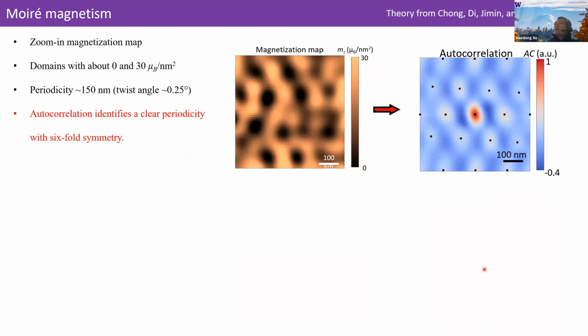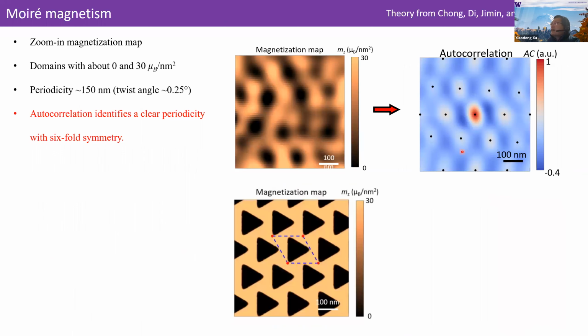So we perform similar data analysis using these autocorrelations. On the left is a magnetization map, and on the right is the autocorrelation. We do see a disordered, but pretty clear, hexagonal pattern. We can also simulate what the magnetization map is going to look like by considering lattice reconstructions. This down here is just a map we show. You can see that in this calculated map you don't see any fuzziness, which really organizes these hexagonal